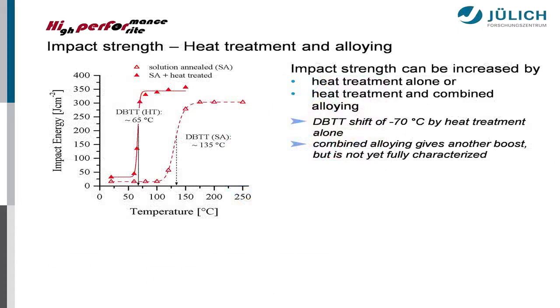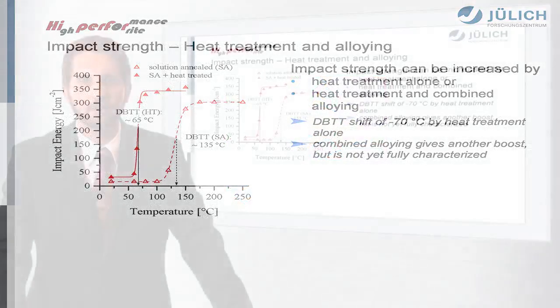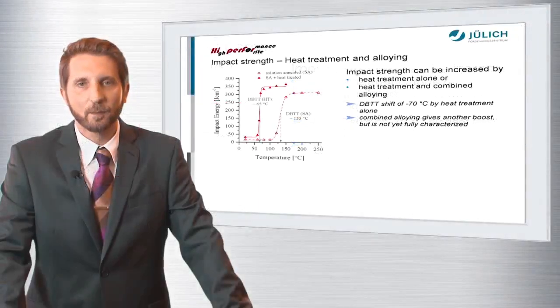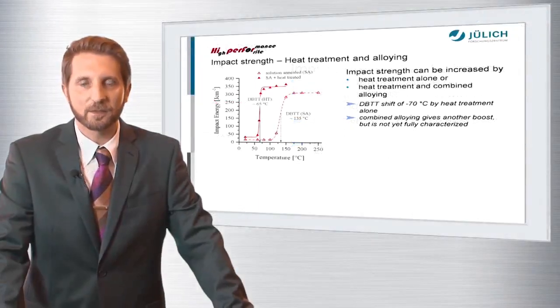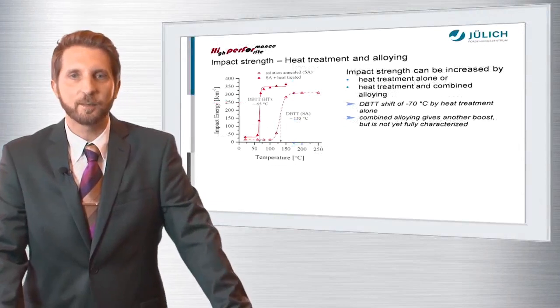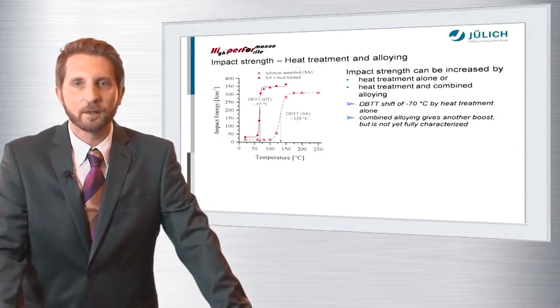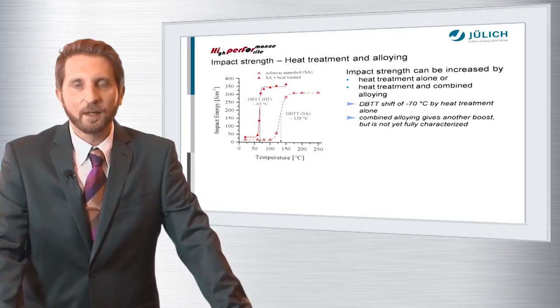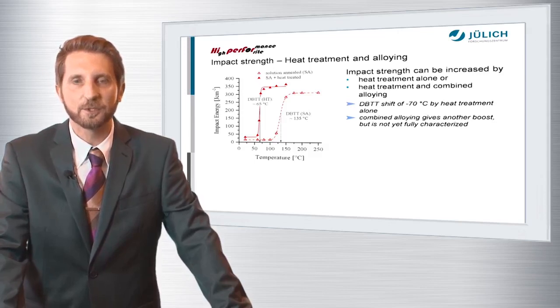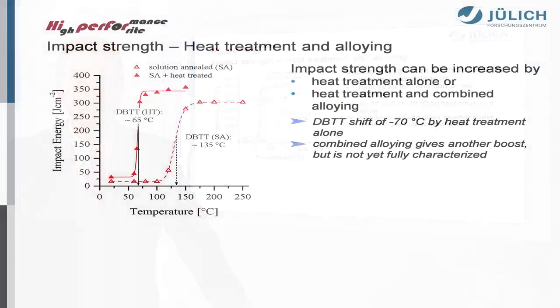So the last thing I'm going to talk about is impact strength. This is a property which is mostly demanded by design codes, which have to be taken into account in power plant construction. And like you can see here, the ductile to brittle transition temperature of our Hyperfer steels in the solution annealed state is not very beneficial. It's well beyond 100 degrees C, namely 135 degrees C, and this is not very desirable.